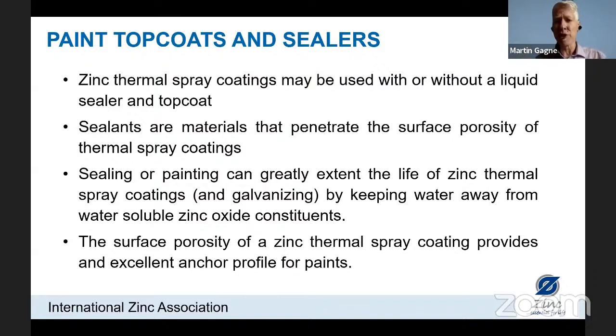Now, if we have the paint on zinc and we scratch through, even if we scratch through to the base steel, the zinc will protect the steel from corrosion, so we don't get these high volume iron corrosion products. We will start to get the zinc corrosion products, but as shown, these will tend to build up in the crevice. So we don't get the pressure on the paint film. So the paint stays intact right up to the scratch or hole. And so in this way, while the paint gives extra barrier protection, the zinc also protects the paint. So we get a much improved longevity of the combined coating.